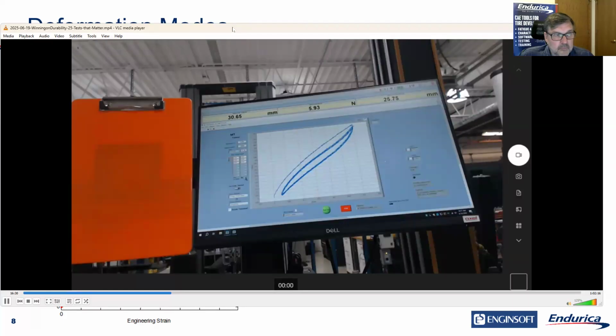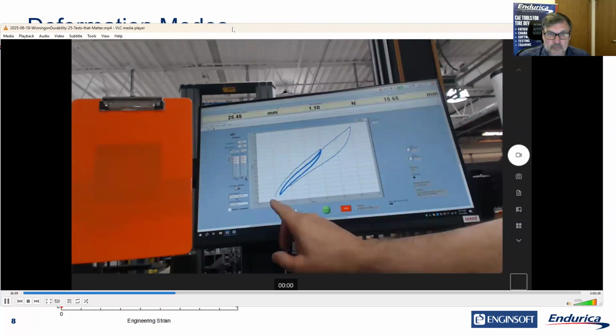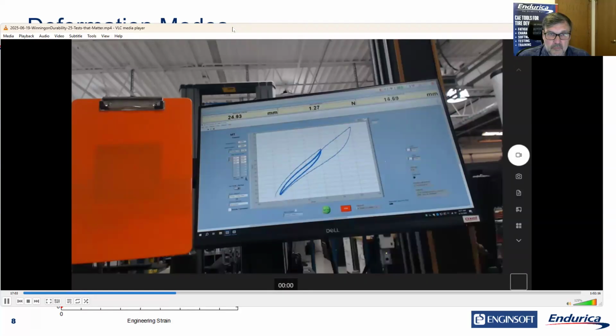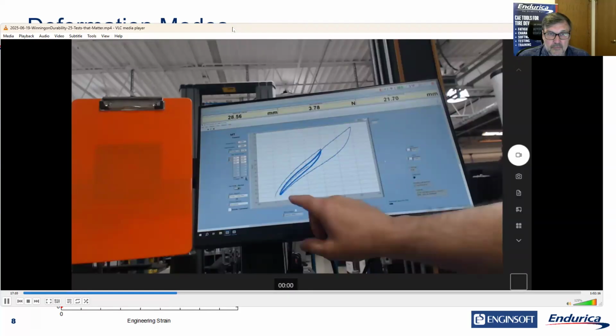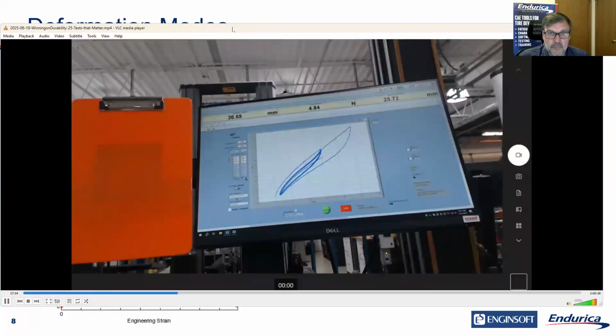This time, we're going to go all the way up to 50%. We were just at 30% strain. So the material changes quite a lot depending on how much it's been stretched. Notice also that we started here, and when we unloaded it, it does not fully recover. So even with very elastomeric elastomers, there can be a little bit of set. As analysts, we have to decide whether I don't care, I'm just going to ignore that and get on with my life, or it's so significant I have to make provisions for that.